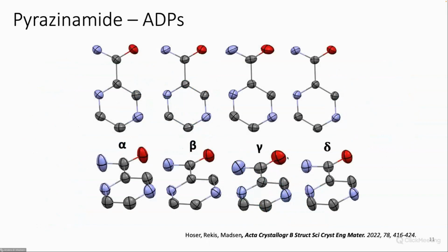So what we have done is to collect a large range of diffraction data. We have collected data at many different temperatures, ranging from 10 Kelvin up to room temperature. Here's a representative look at some of the thermal ellipsoids. We have removed the hydrogens to make it a bit clearer here. The thermal ellipsoids of pyrazinamide in the different forms here are at 123 Kelvin and at the 90% probability level, so that you can easily see what's going on.